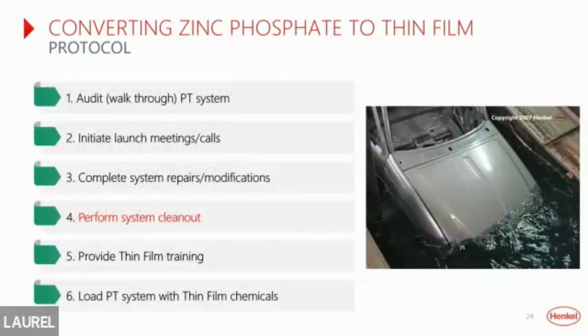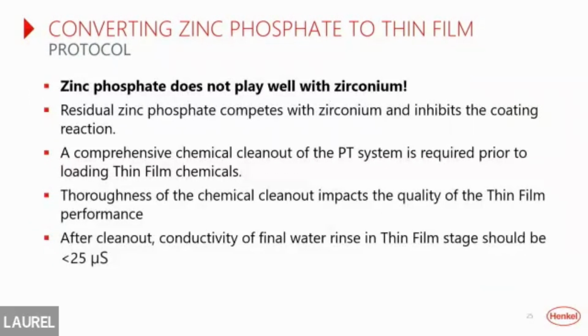Next is the system cleanout. I think most of us know, and if not, I'll tell you now, zinc phosphate does not play well with zirconium. We need to make sure that all of the zinc phosphate, or as much as physically possible, is removed before the zirconium is loaded. Too much phosphate will compete with the zirconium and inhibit the deposition of a uniform coating.